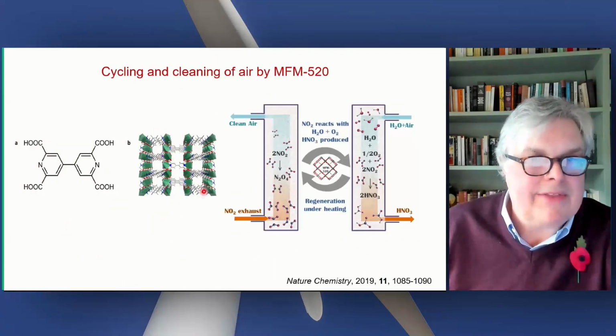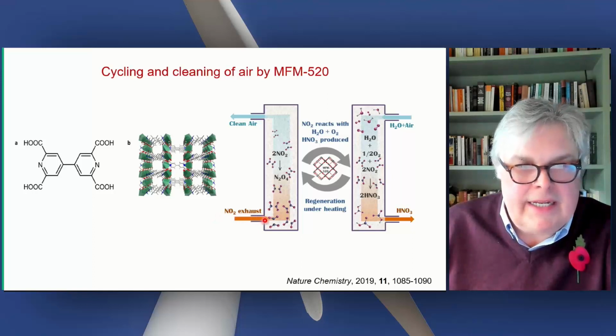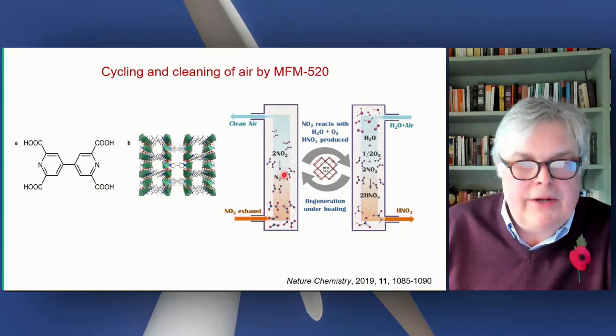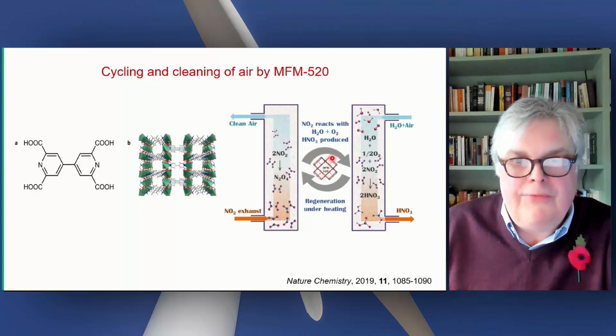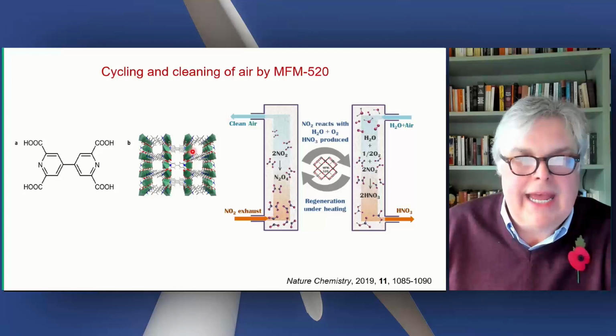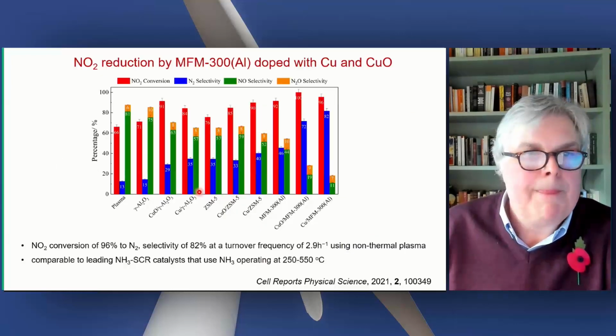And so we can take this MOF, feed it an NO2 exhaust. The NO2 goes into the framework as N2O4, clean air comes out. The N2O4 can then be transferred into a flow of water and air. The oxygen in the air oxidizes this up to nitric acid. So NO2 goes in, nitric acid comes out, clean air comes out.